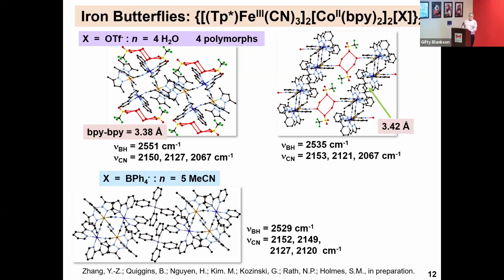There's one where we attempted to get rid of all the water and hydrogen bonding by inserting something called tetraphenylborate, an anion, where you have a central boron with a formal -1 charge, and then 4 phenyl rings, C6H5, attached to that anion. All the structures are different, and that was kind of annoying, but the important thing is, even if we remove the lattice water or other solvents or other anions, we got things that had different spectroscopic properties, but none of them showed electron transfer. But from electrochemical studies, we predicted that this combination of ligands on iron and on cobalt should do electron transfer. So something else is important.